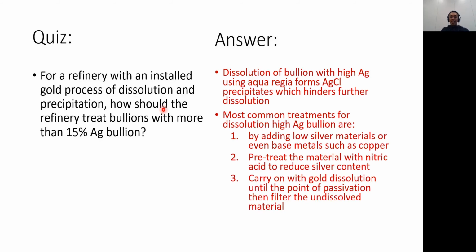So the answer is like this. As we know, the dissolution of bullion with high silver using aqua regia is very hard, because silver chloride is not dissolved there, and it precipitates, which hinders further dissolution. So there are some options. The most common treatment, the industrial practice for this high-silver dissolution, is to add low-silver material or even base metal, for example copper scraps or silver scraps that they have from their process.